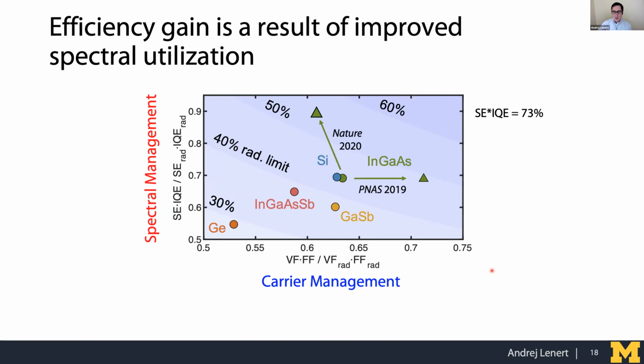All right, so let's go back to this plot of spectral versus carrier management and see where we ended up. So our work pushed, as I mentioned, into this high-efficiency spectral management regime. And we made significant gains in that direction. And we were able to surpass and approach about 55% of the radiative limit. And I want to acknowledge that we pushed along different facets of this problem relative to the Berkeley group, but there's no reason why these two can't be merged together.